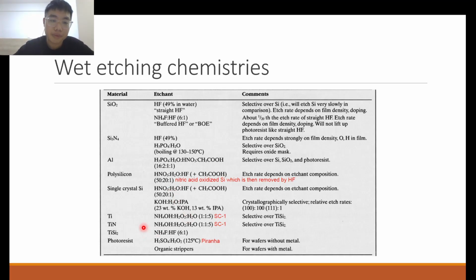For Ti, we can use SC1. TiN, also a very common conductive contact used in semiconductor devices, is also SC1. Your titanium silicide, also a very common contact material, you can use this buffered oxide etch kind of combination. For photoresist, the Piranha solution that we mentioned earlier already.